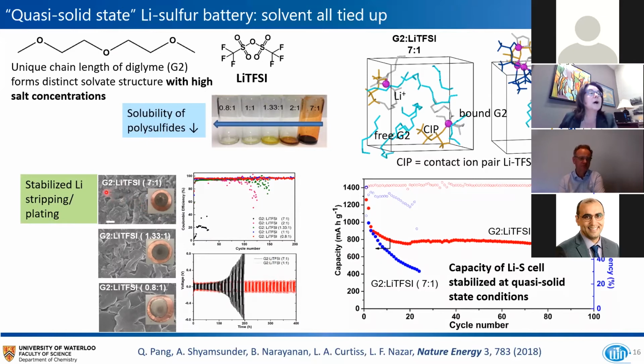So when we have high solvent ratios to salt ratio, we see a lot of dendritic growth, we see passivation and basically degradative reactions at the negative electrode. We're depositing on copper here. Whereas when we have very low concentrations of the electrolyte or high concentrations of the salt, we see fairly clean deposition. And this is shown by these stripping plating experiments and by the fact that we have coulombic efficiencies approaching 100%. And best of all, the capacity of real cells is effectively stabilized at these quasi-solid state conditions.